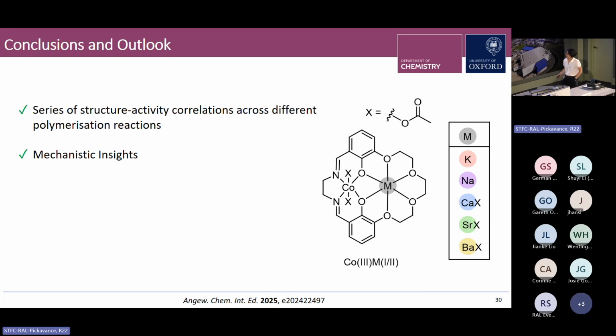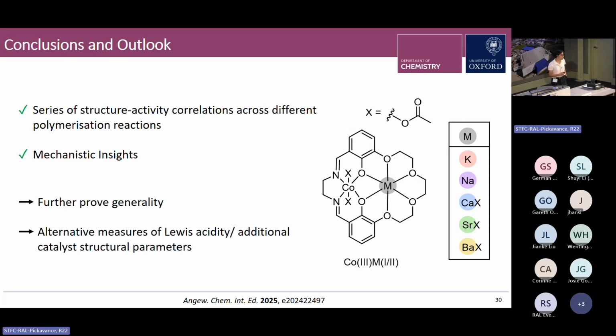But there's a lot of work still to do in this area, so we'd like to further prove the generality of these correlations for different catalysts and different polymerization reactions. And in particular, we're looking for a new x-axis, so a new measure of S-block metal Lewis acidity, or an additional catalyst structural parameter that we can correlate to catalytic activity that crucially is measured within our specific complex rather than a pKa value taken from the literature. And that's also the topic of ongoing work in the group at the moment.